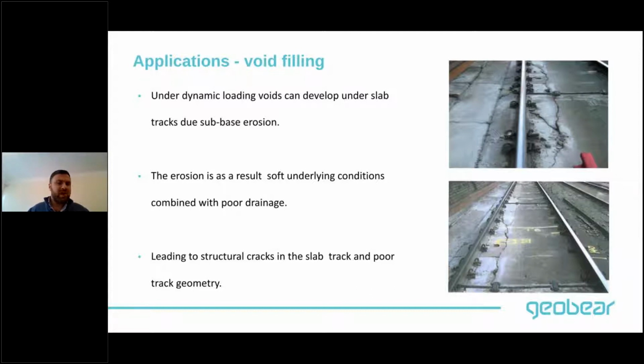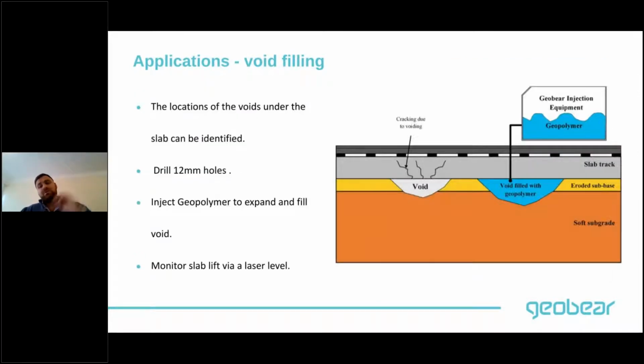Some slab track systems do have some mechanisms that allow you to lift the track a little bit, but they're quite limited. What we can do is, if we know the locations of the voids, which could be found via site investigation or geophysics investigation, we can then drill into these voids and insert 12 millimeter diameter tubes into these slabs to start injecting geopolymers into these voids. The geopolymers will start filling those voids, and also if there's any water there, it will start pushing that water away from the void and fill the void completely.